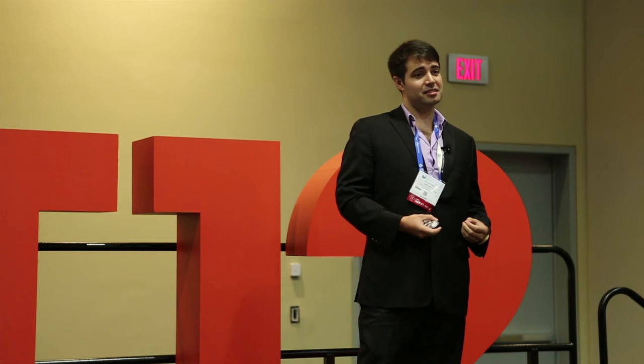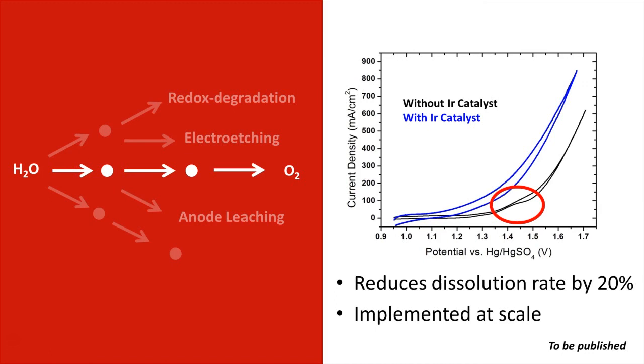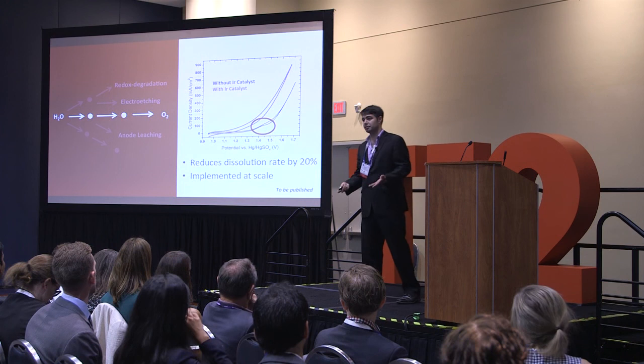When I walked into a zinc plant and said 'I want to sell you a water oxidation catalyst,' they said, 'a water oxidation what?' After a little rebranding — 'I want to sell you a corrosion-resistant layer' — they said, 'we'll buy it.' Electrochemically, using cyclic voltammetry, we vary the potential and measure the current from the anode. The approach targets the redox features representative of lead solubility — for example, the Pb3+/4+ redox couple — and when you put an iridium catalyst on the anode, that redox feature goes away. Longer-term experiments confirm it actually reduces anode corrosion, and we have implemented this on a decent scale.